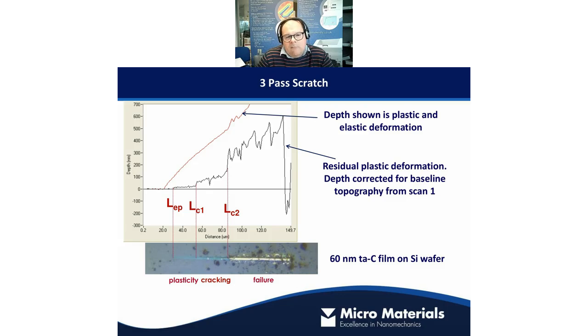Then we do our ramped load scratch, and this is our ramped load pass here. What's happening is as the load increases, the depth increases. We can see at a certain point an event occurs. At this point, we don't really know what that event is, potentially. You can see that something's happened, but we need to wait until the completion of the test to get a full picture. So the final pass, the third pass, is another low load topography. We do a low load topography before our loaded pass scratch, and we do one after the loaded pass scratch. So this line here is our post-scratch topography, okay?